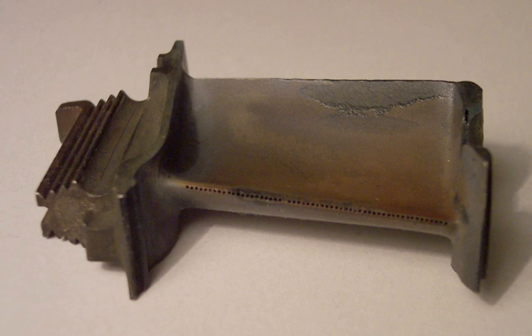In addition to solid solution strengthening, if grain boundaries are present, certain elements are chosen for grain boundary strengthening. B and Zr tend to segregate to the grain boundaries, which reduces the grain boundary energy and results in better grain boundary cohesion and ductility. Another form of grain boundary strengthening is achieved through the addition of C and a carbide former, such as Cr, Mo, W, Nb, Ta, Ti, or Hf, which drives precipitation of carbides at grain boundaries and thereby reduces grain boundary sliding.